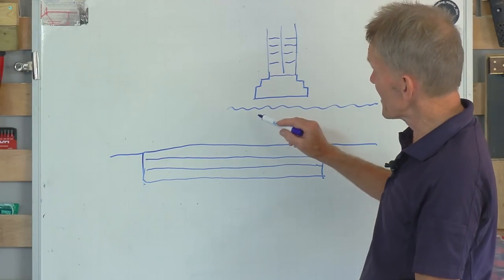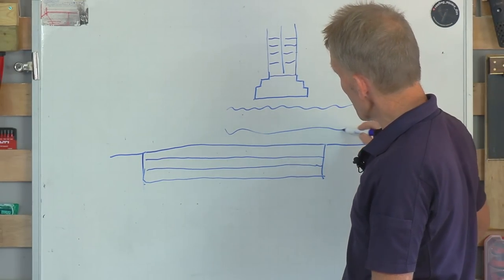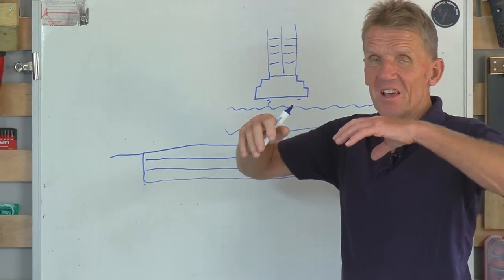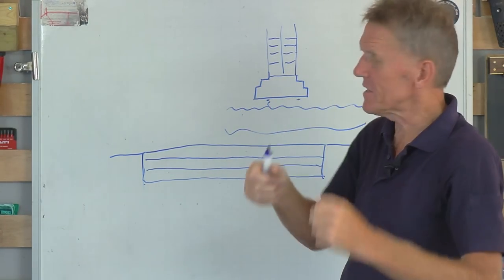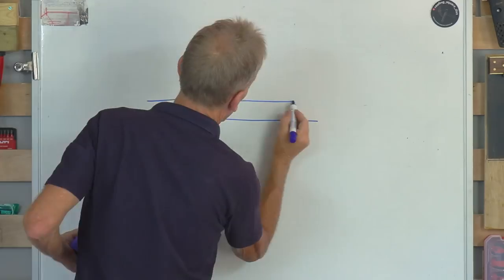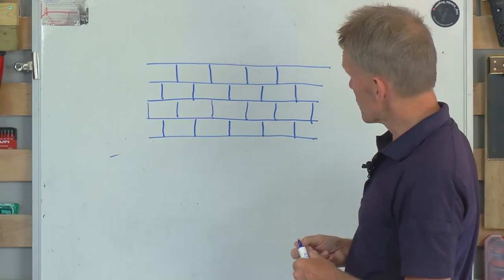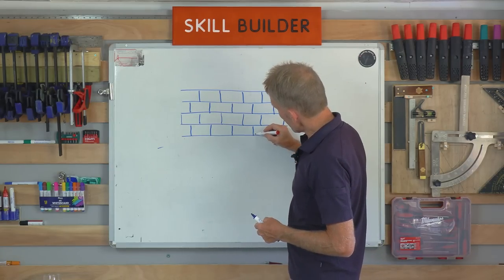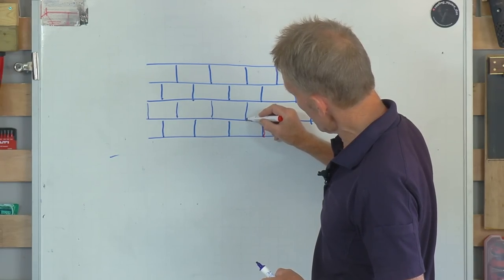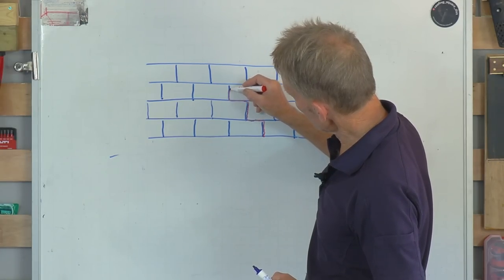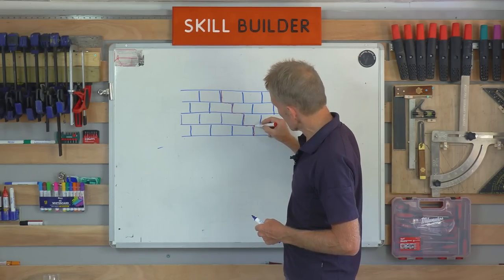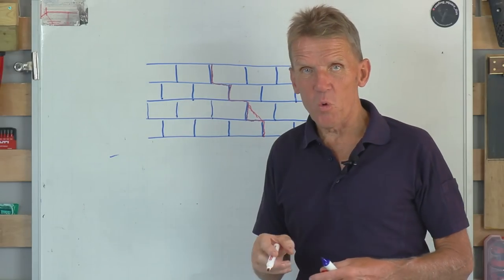And of course as this clay shrinks, dries out here, that wall will be unevenly supported. The clay has shrunk, it's cracked in places and your foundation will follow it. And you will notice on your brick wall that you have a crack along the mortar line going up there, going up there, going up there, and going up there if you're lucky. Every so often it might take a bit of a shortcut and go across one of your bricks.